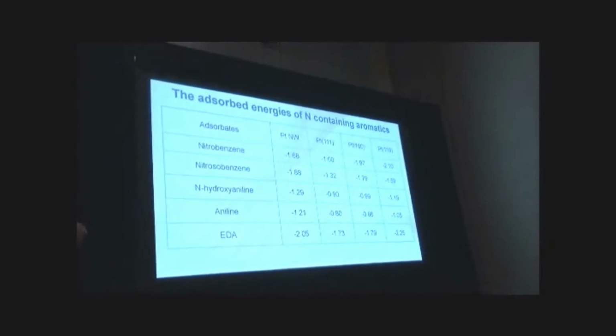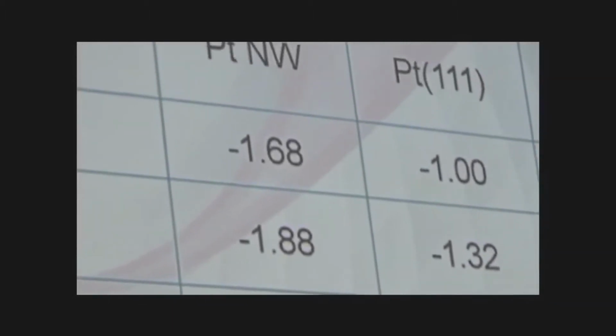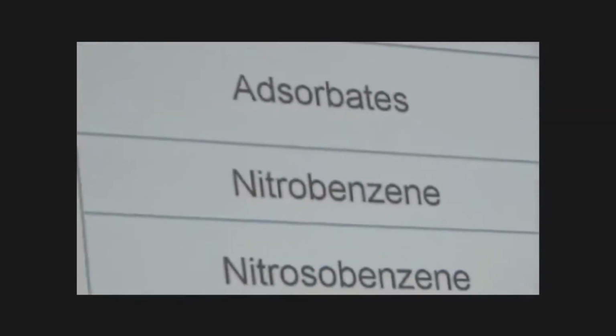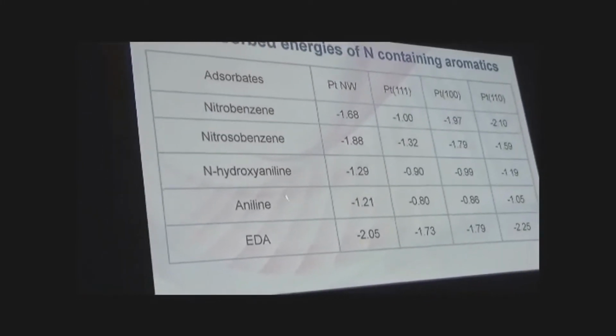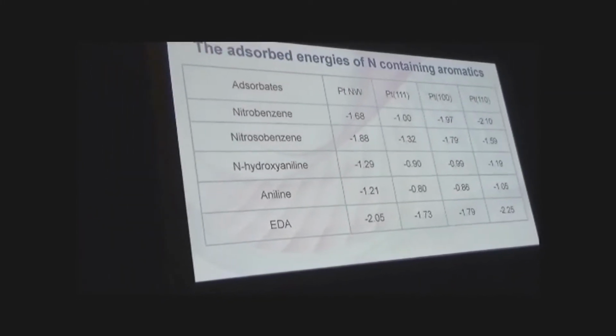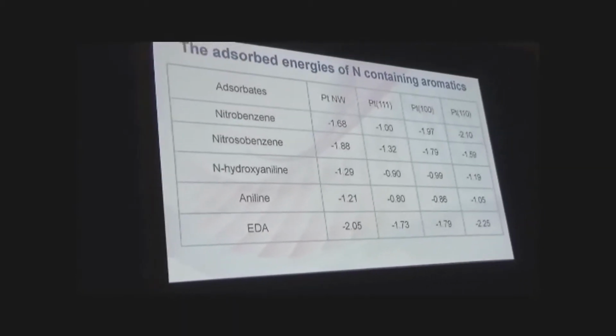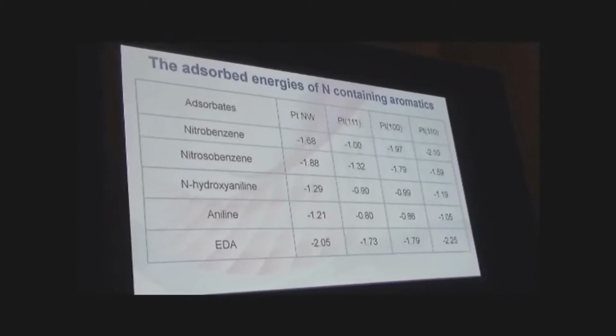However, when we compare the absorption energy of different intermediates of nitrobenzene on the Pt nanowire and the Pt111, Pt100, and Pt110, you can see that there is no significant difference between them. So all of them can strongly absorb on the surface. What's the origin of the selectivity? We should be missing something.